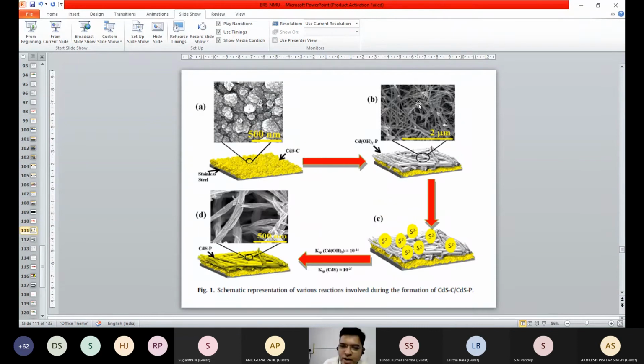In order to have the nanowire, initially we deposited cadmium sulfide in the compact form, because for the supercapacitor application we have used liquid. So liquid should not penetrate through a porous area, right? And we can get certain nucleation sites for the cadmium sulfide nanowire. We have deposited cadmium sulfide with this nanopebble-like morphology on the stainless steel. Then we have coated cadmium hydroxide nanowires on these cadmium sulfide nanopebbles.